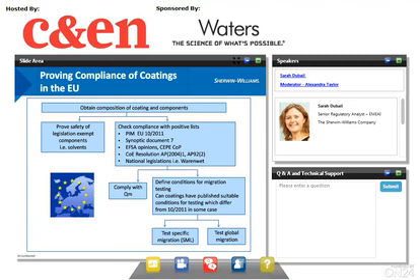The global migration limit is also in place at 60 ppm, 60 milligram per kilogram of food, and the test is designed to prove inertness of the material. The simulants for migration testing are chosen depending on the final use of the packaging. Can be, for example, 10% ethanol, 3% acetic acid, rectified vegetable oil. To some extent, the conditions used for can coatings are close to the testing conditions described in the PIM 10/2011, applicable for plastics, but it differs in some cases.